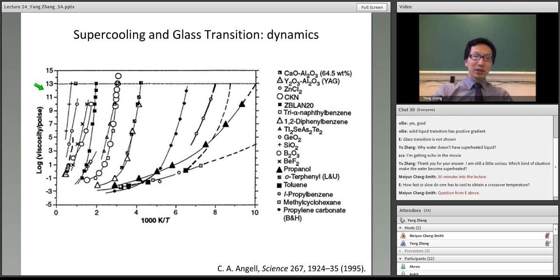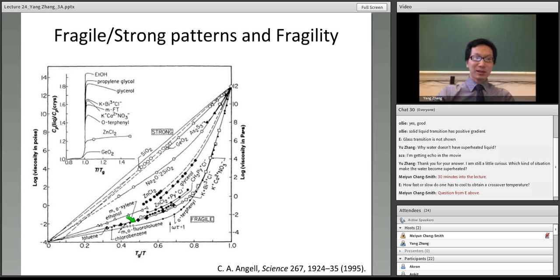So it's natural to think about how to scale the temperature here. Now we use 1000 over T, which is basically 1 over temperature. One trivial temperature to scale this figure would be the temperature at the critical point, which is uniquely defined. You can also use the temperature at the triple point, which is also uniquely defined, to do the scaling. But unfortunately, for many of these materials, it's not easy to get the triple point or critical point temperatures. At least we cannot get all of them. But this temperature is very close to the glass transition temperature, and we know the glass transition temperature by experience. So what we can do is scale this temperature with their corresponding glass transition temperatures, and that gives this famous plot from Angell.